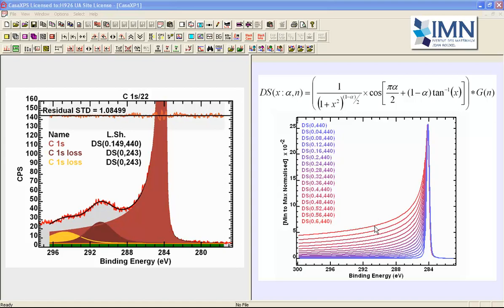The problem is that when we want to calculate a peak area from a region or a Voigt function, there's an interval that is specified over which we do the integration. So the integral of the signal above background will give a value. However, if we integrate over the same interval these line shapes, then the area that we determine from the different line shapes will vary as a function of this asymmetry parameter. This means that there is no systematic way of calculating the intensity of this carbon-1s graphitic peak when we want to compare it against the satellite peaks.